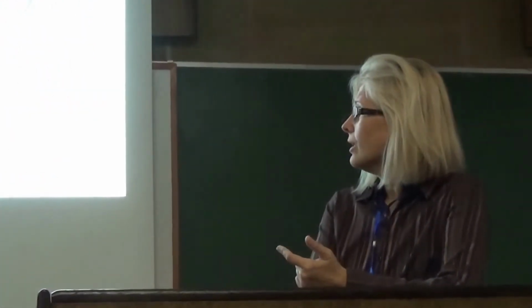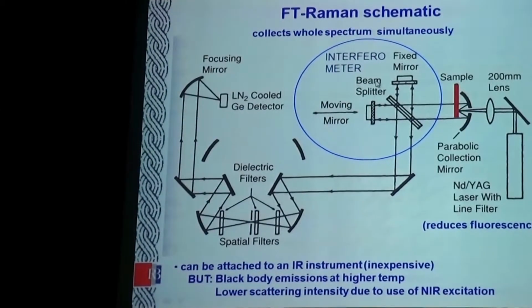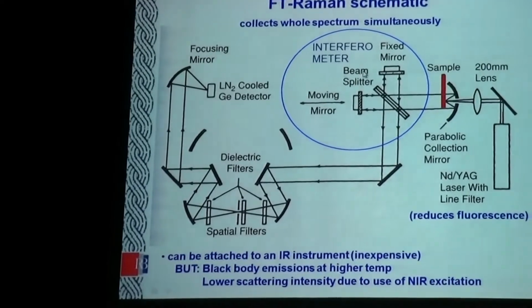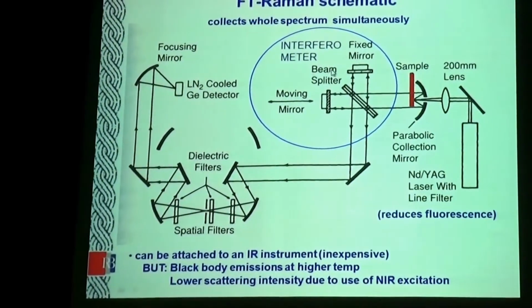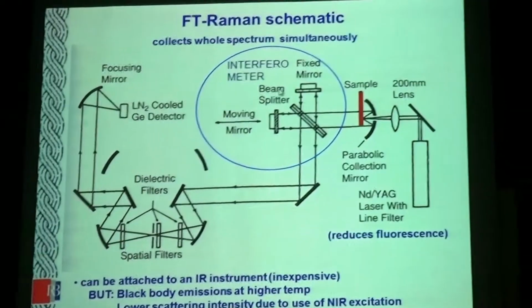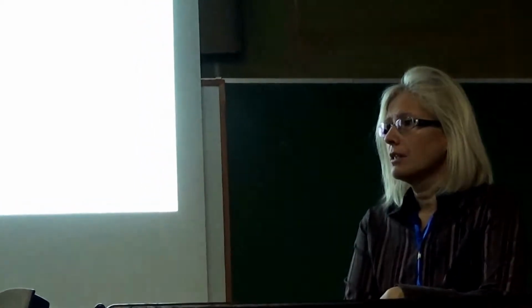Because you can attach it to other things, you can get an idea, but the spectrum is much lower in intensity. It is of worse quality, and the spectral resolution of such instruments is usually 4 inverse centimeters. In our case, spectral resolution is 0.1 inverse centimeter, so sometimes you cannot recognize your lines.